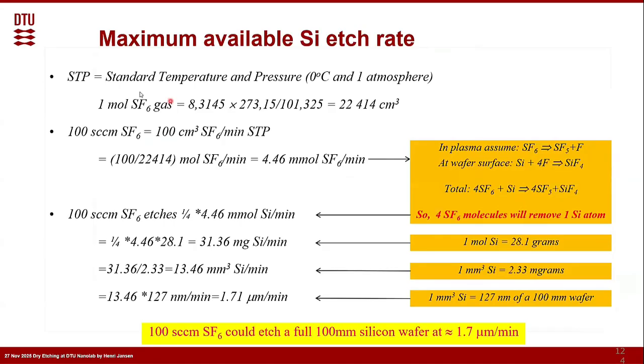Well, first we have to understand that STP, standing for standard temperature and pressure, that means at 0 degrees and 1 atmosphere, for that case, 1 mole of SF6 gas, which is the gas constant times temperature divided by the pressure, is roughly 22 liters of volume. So taking that, we know that if we have 100 SCCM, standard cubic centimeter per minute, STP, SF6 is about 100 cubic centimeter of SF6 per minute STP. And then we fill in this. That means 100 divided by this 22 liters per mole, SF6 per minute. That means 4.46 millimole SF6 per minute. So this is what we supply.